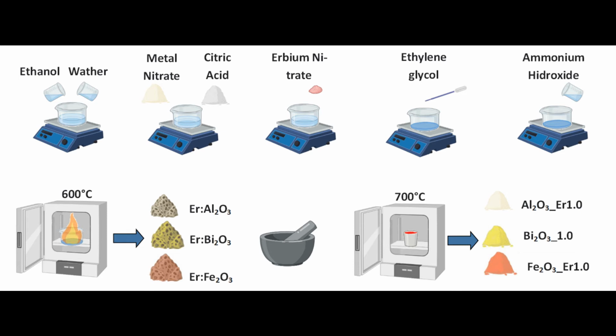The gel obtained was burned in a preheated muffle at 600 Celsius degrees for 5 minutes, obtaining a low-density sponge, and after being crushed, calcined at different temperatures to obtain the optimal phase for each material.